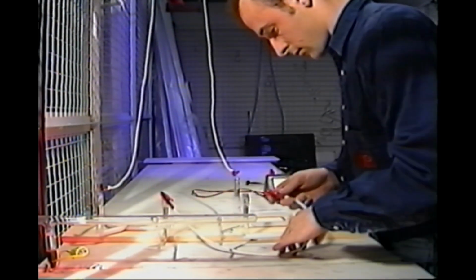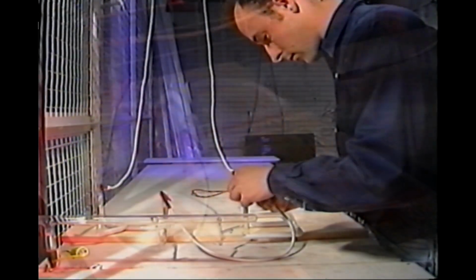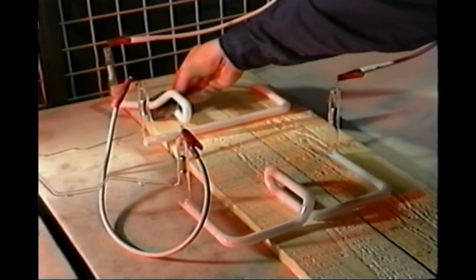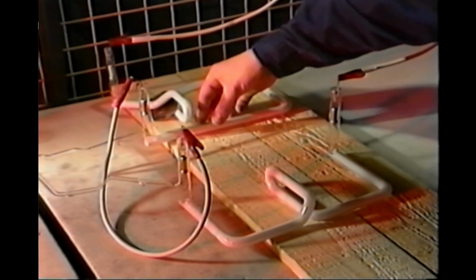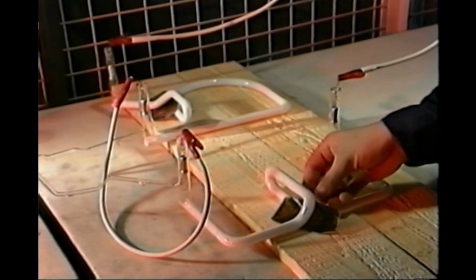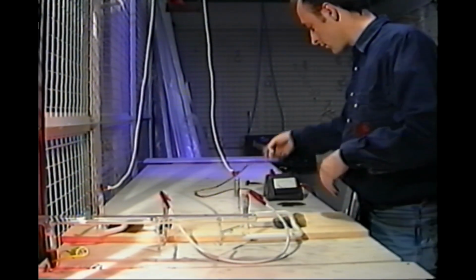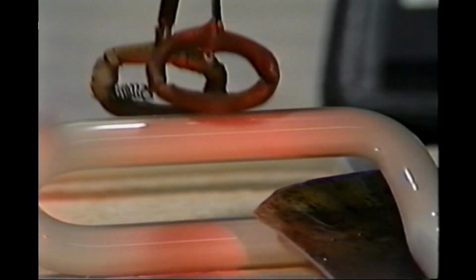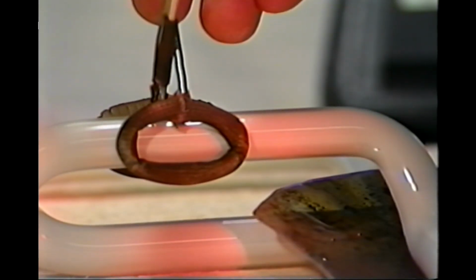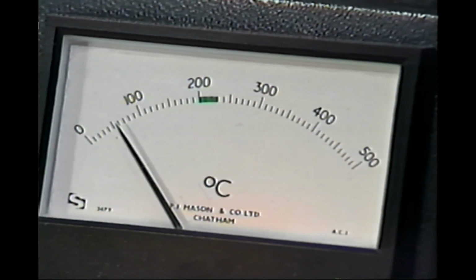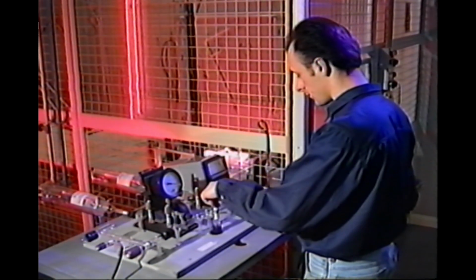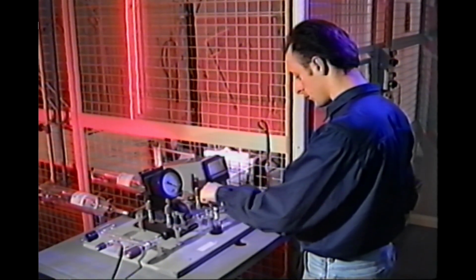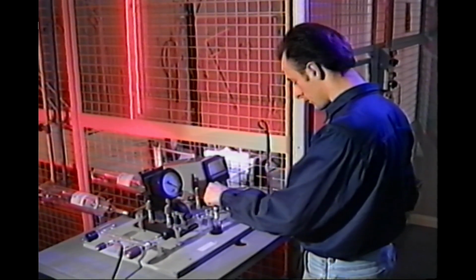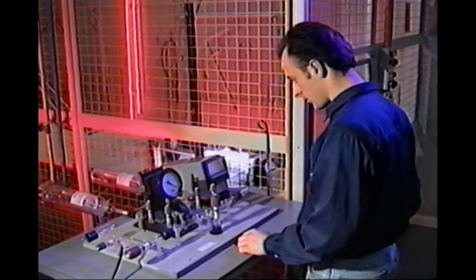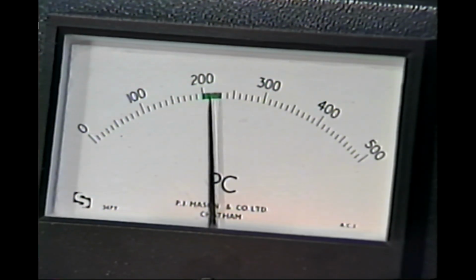Connect the electrodes to the high-tension leads and insert bombarding mica into areas where tubing runs close together as a precaution against arcing through. Next, connect a reliable temperature indicator at the center of one of the tubes. A good quality temperature gauge and thermocouple is recommended for accurate measurement. A piece of paper is a popular way of judging tube temperature, but is notoriously inconsistent, as different types of paper will give different indications.